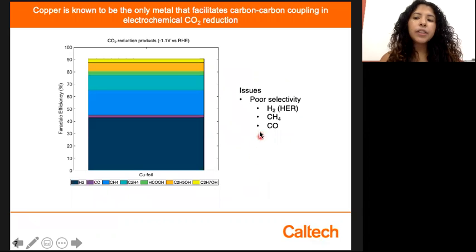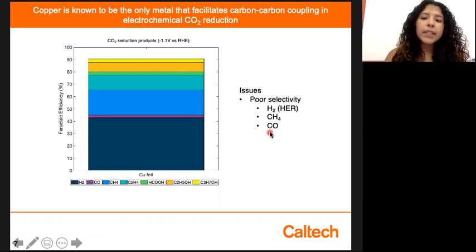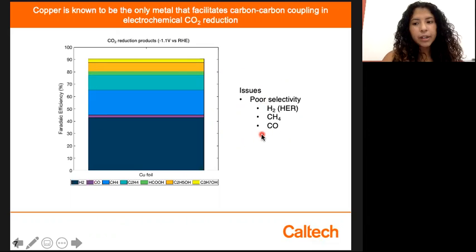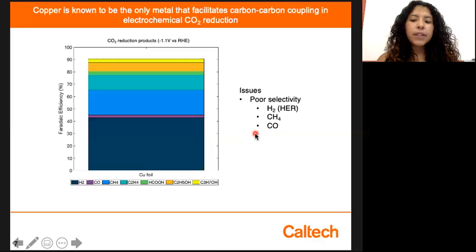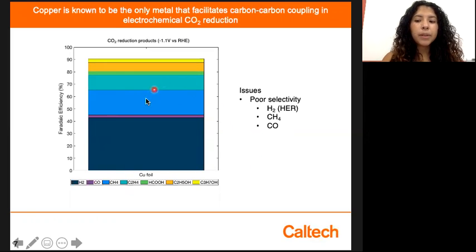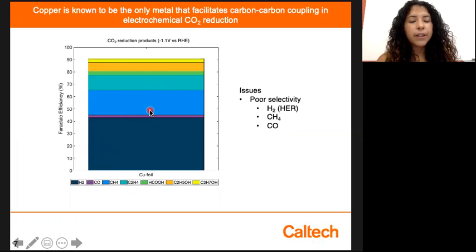And today, copper is the only known transition metal to be a great heterogeneous catalyst for CO2 reduction because it can facilitate the formation of multi-carbon products by C-C coupling on the surface of the electrode. But the main issue with copper is that it is not very selective because, as you can see right here, the main products being made on a bare copper electrode are hydrogen and methane, making up over 60% of the total Faradaic efficiency. Meanwhile, ethylene only makes up a little bit over 10%.